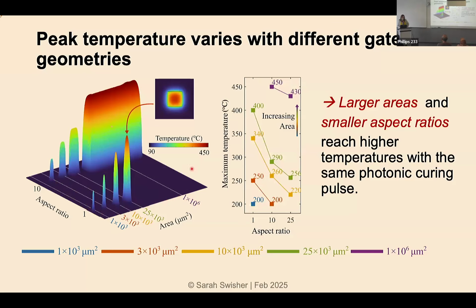And yet we see that a larger area device, so as we go up in area, we get higher peak temperatures. And as we go down in aspect ratio, so this device and this device have the same area, but this one is a rectangle with an aspect ratio of 10, and this is a square with an aspect ratio of 1. You can see even with the same area, a high aspect ratio gate doesn't get as hot.